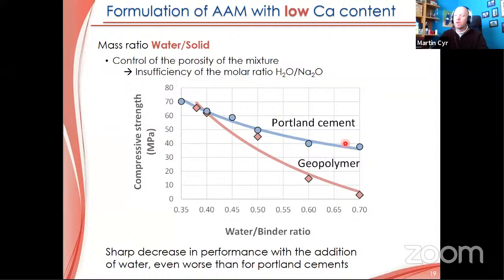We see here the well-known effect of water-cement-binder ratio for Portland cement. We see that we can be around 60, 70. And if we increase a lot, of course, it will decrease the strength, but it will reach around maybe 40 MPa.